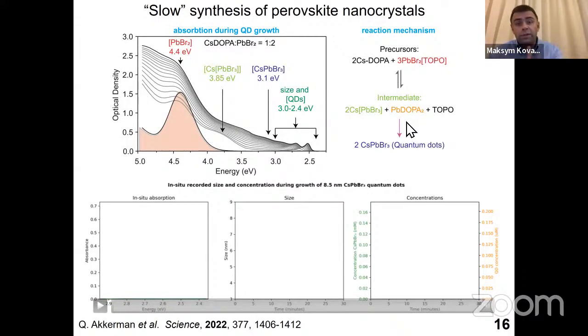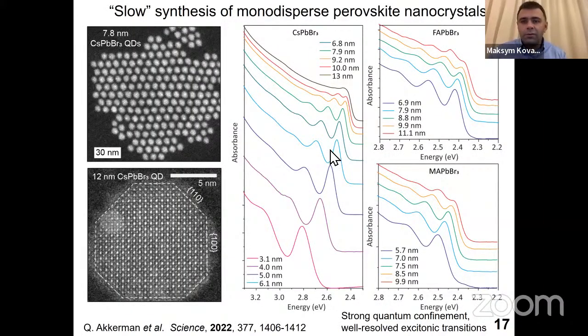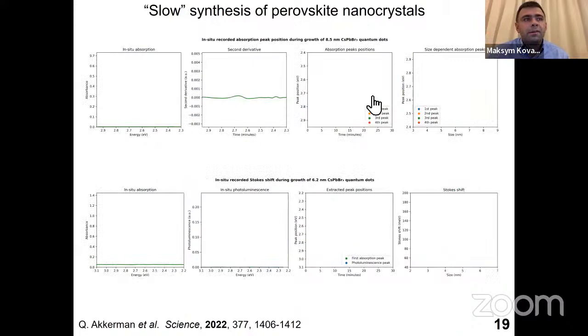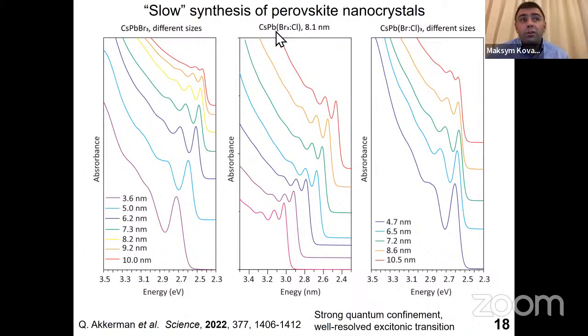The curse, of course, is that you have to do it rapidly, because otherwise nanocrystals after the growth will start coalescing and recrystallizing to bulk material. In this case, right after you reach the plateau in the nanocrystal formation, you now add the ligand of choice and you can stabilize nanocrystals. Any ligand that we used before, as well as any ligand which we will discover in future, can now be tested in a very rational manner through this approach. So this brings me to the surface studies. By the way, just to show you that you can also produce mixed halide compositions by mixing bromides and chlorides, you can then tune the band gap by the composition, or by size, or by composition.